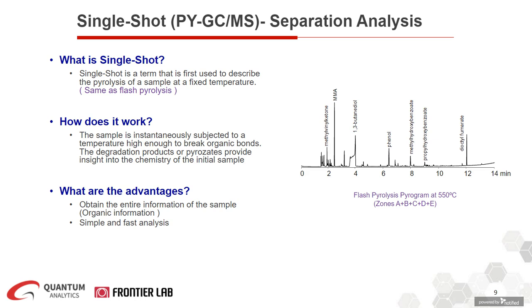So using the EGA of the eyeliner from the previous slide, we identified the optimal temperature for the single shot at 550 C. So 550 C is the optimal pyrolysis temperature. In this case, you're not performing over-pyrolysis or under-pyrolysis on your sample. That's where EGA comes in. It's a very, very important first step for you to understand what the optimal temperature is for your flash pyrolysis, for example.